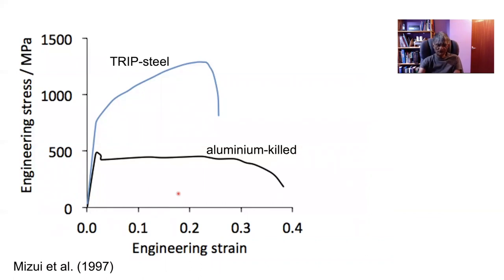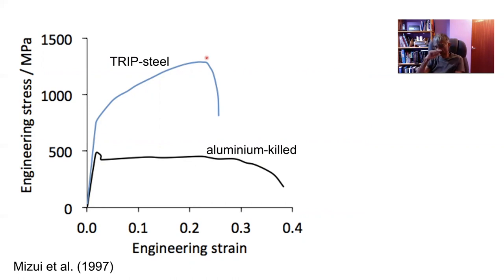About 20 or 30 years ago, many cars were made using a steel with a strength of the order of 500 megapascals. You can now get TRIP steels — transformation induced plasticity steels — which are much stronger and show a much greater extent of uniform elongation, certainly sufficient to form the sort of parts illustrated earlier. The question is: why does this steel have significant ductility in spite of being almost two or three times the strength of what used to be the case 30 years ago?